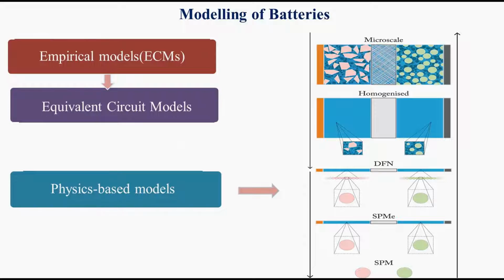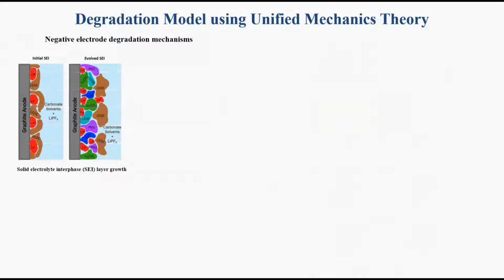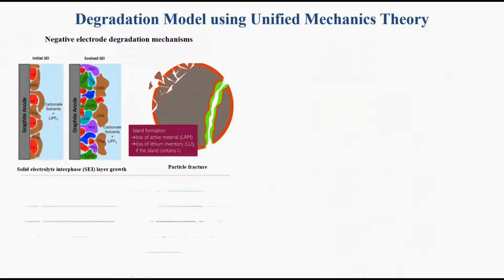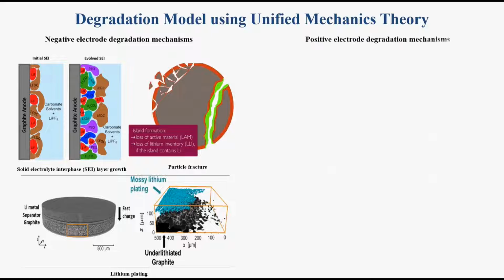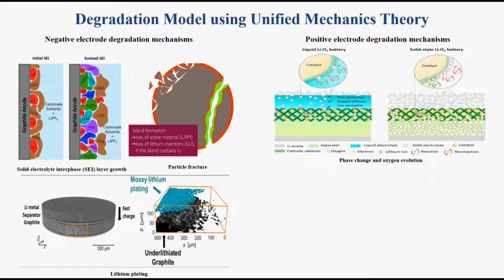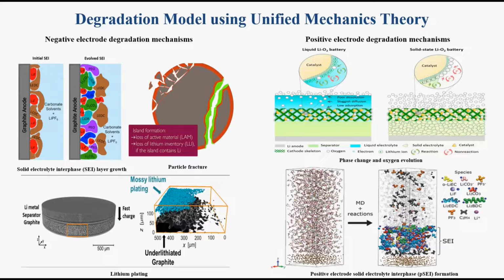Different types of physics-based models are the microscale model, homogenized model, DFN model, and single particle model. A degradation model takes into account all the degradation mechanisms at the positive and negative electrodes like formation of solid electrolyte interface, phase change, oxygen evolution, particle fracture, and lithium plating. We at the SMILES lab are attempting to model the degradation of batteries used in electric vehicles using unified mechanics theory.